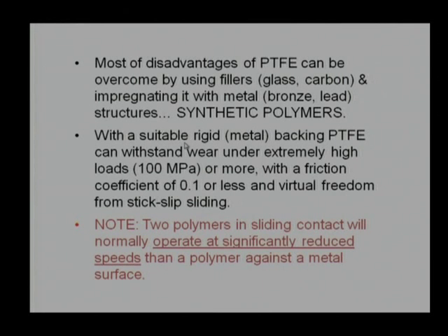It has also been mentioned here that with a suitable rigid backing, PTFE can reduce the wear and withstand high temperature and high load, that is, a stress level of even 100 megapascal, while still maintaining a low coefficient of friction. The coefficient of friction is consistent: the static coefficient of friction and the kinetic coefficient of friction are almost the same when we are using PTFE. That is a major advantage of PTFE.